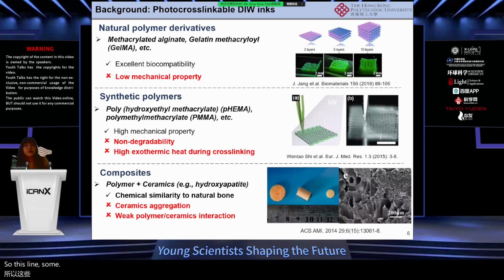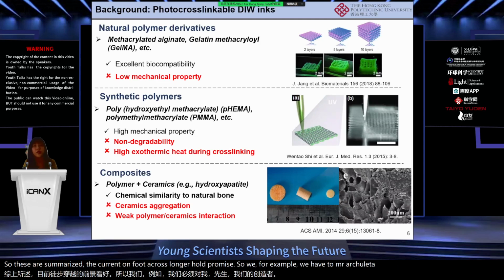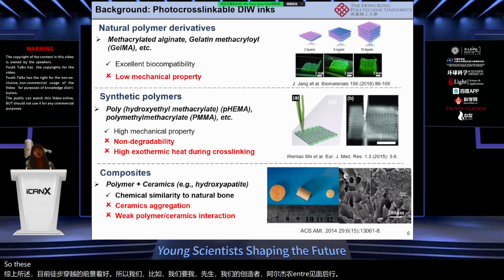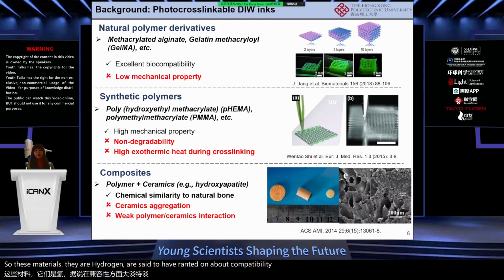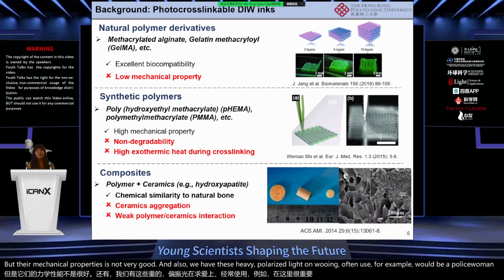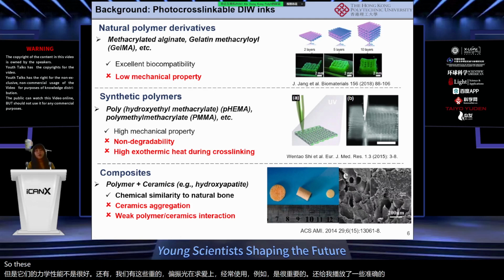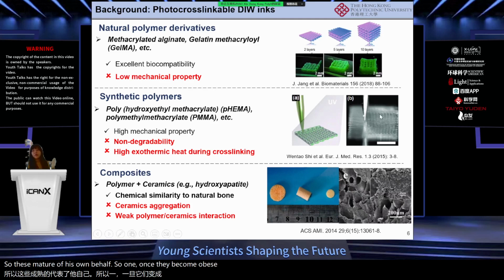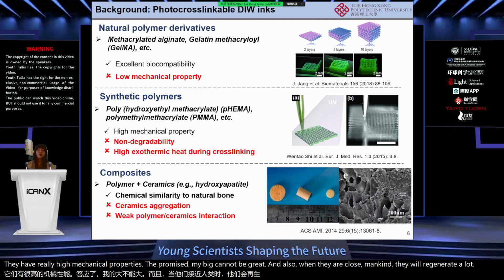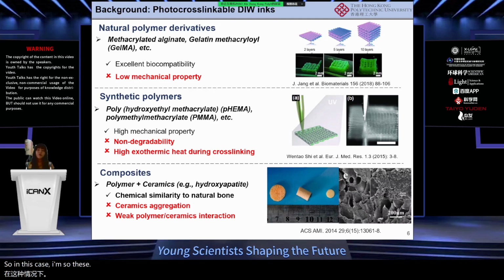This slide summarizes the current photocross-linkable polymers. For example, we have methacrylated alginate or gelatin methacryloyl. These materials are hydrogels, so they have very good biocompatibility, but their mechanical properties are not very good. And we also have synthetic polymers, like what we often use, for example, polyHEMA and also polymethyl methacrylate (PMMA). Once they go from liquid to solid, they have really high mechanical properties. The problem is that they cannot degrade. And also when they are cross-linking, they generate a lot of heat, so this heat will also compromise the loaded bioactive molecules.